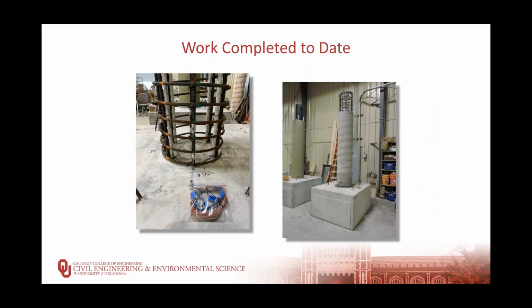We also installed strain gauges on the longitudinal steel for our traditional reinforced concrete column that serves as a control specimen. We located the strain gauges at the approximate same locations as those that were installed on the inner steel tubes for our novel column design. And then we cast the concrete for that column so that it's ready to be placed in the test setup. The concrete for this column had a 28-day compressive strength of 6,000 PSI to match a typical Oklahoma Department of Transportation bridge column.